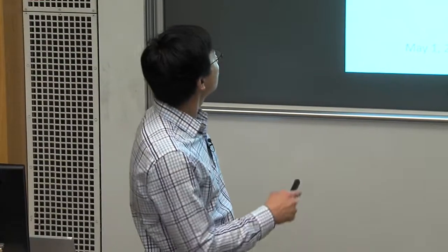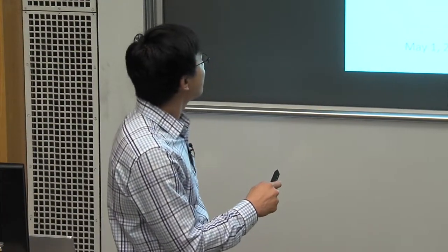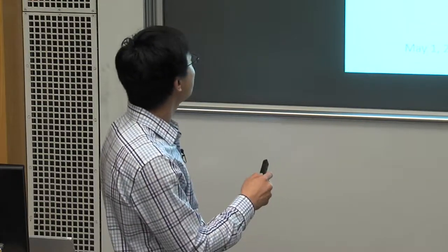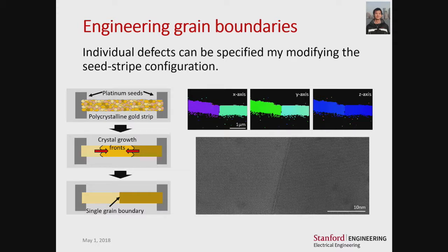Here I just want to give you an example of something we're working on right now, where we are ultimately creating ideal systems for producing single defects. So here, instead of having just one platinum seed, we have two platinum seeds. And as we heat this up and liquefy the gold and let it cool, we now get two crystal growth fronts. And as these two growth fronts propagate and ultimately meet in the middle, we have a single grain boundary.